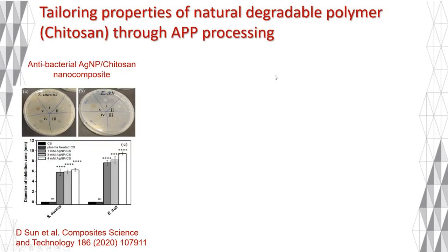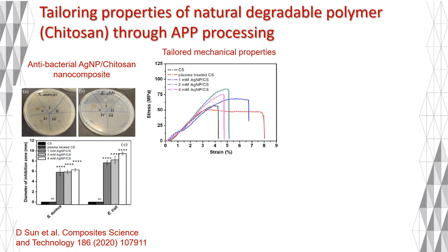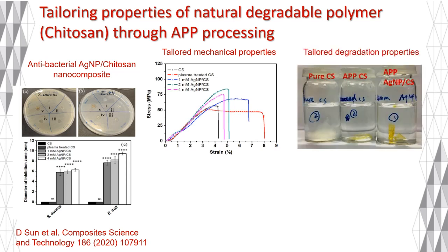Apart from deploying various synthetic polymers for creating our functional composite system, we also made an intriguing discovery during our research involving natural degradable polymers such as chitosan. Chitosan, derived from natural materials such as chitin, found in abundant natural resources like shells, is a natural polymer with unique properties. Through our well-established plasma technique, we successfully synthesized a silver chitosan composite and demonstrated its effectiveness in antimicrobial applications. An interesting observation that emerged from this study is that the plasma treatment itself can also significantly modify the chemical structure of chitosan and consequently influence its physical and mechanical properties.